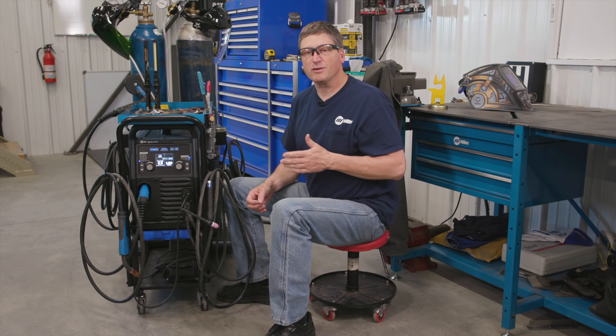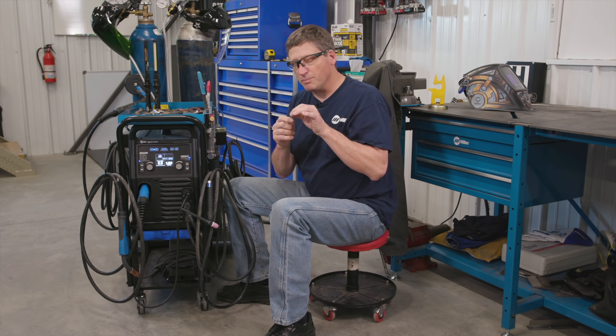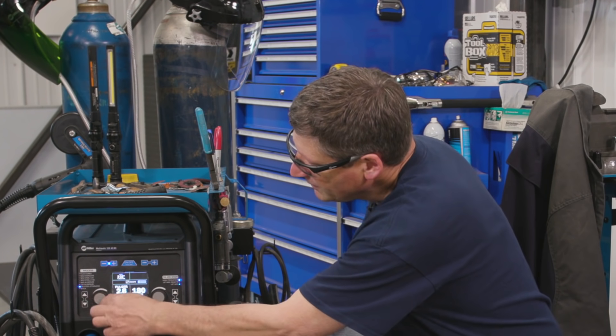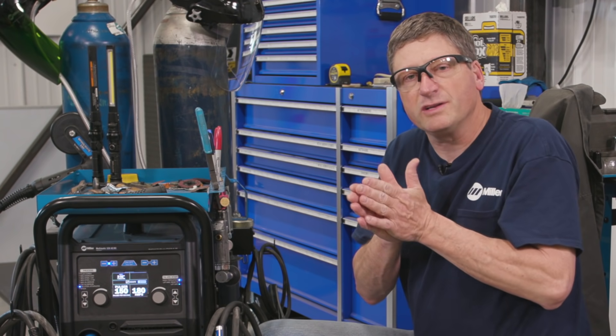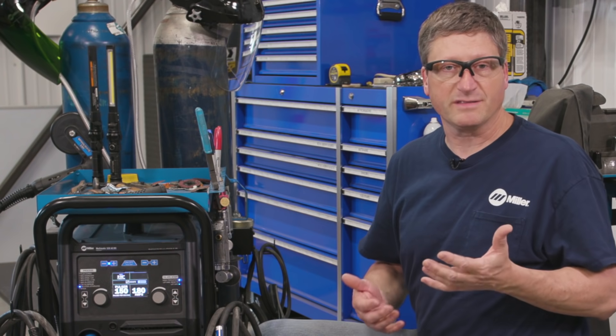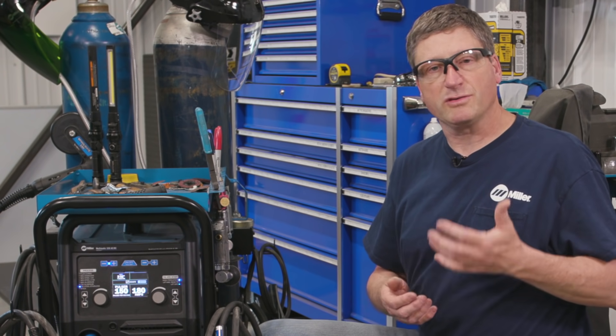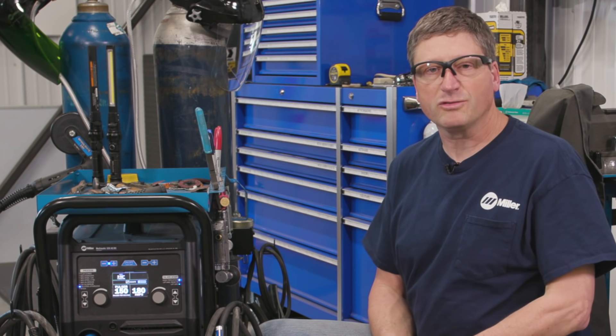If I run a little faster — 1.2 or 1.3 pulses per second — that helps me add rhythm to my weld puddle. Every time the machine pulses high I'm dabbing the filler metal in, so it gives you a very consistent weld puddle look. You can run the pulser up to 150 on this machine. The faster the pulses the tighter the ridges are going to look in your weld puddle, and an added bonus is it shakes the weld puddle and gives you a better grain structure of the weld bead. So if you're welding dissimilar steels — chromoly and mild steel for example — it might behoove you to run the pulses up pretty high to agitate the weld puddle and give you a stronger weld bead.